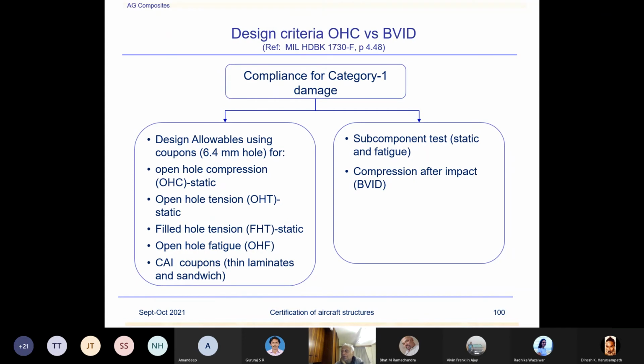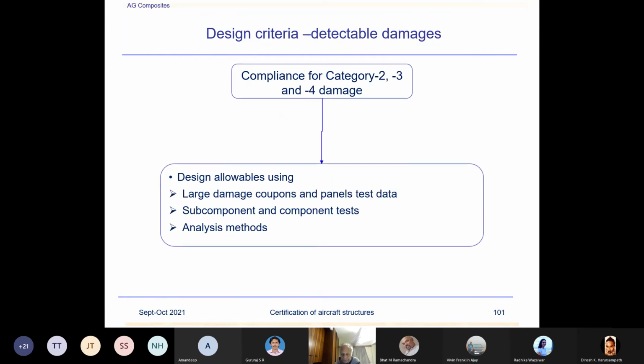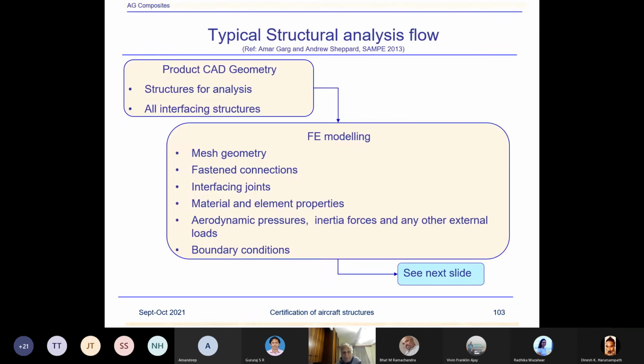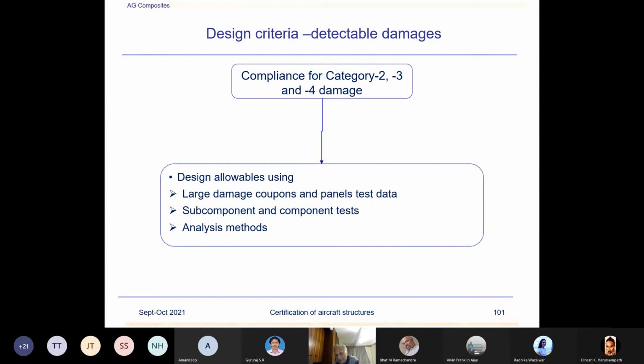And that is how we develop the compliance philosophy. Determine the allowables with these damage sizes and determine the residual strength we require at least. Subcomponent by subcomponent test, coupon test, compression after impact test. Categories 2, 3, 4: design allowables using large damage coupons and panels test data, subcomponent and component test and analysis methods. Analysis. Any questions so far on these damages?